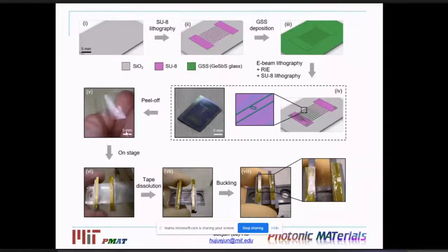We then delaminate this substrate from the handler substrate using water-soluble tape. We then mount them on a mechanical motion stage. And then we use a microcontroller to precisely control deformation during the buckling process. And after that, we get an array of little mechanical sensors that can now be embedded into a three-dimensional tissue model.